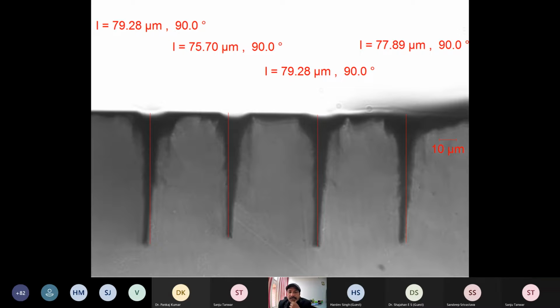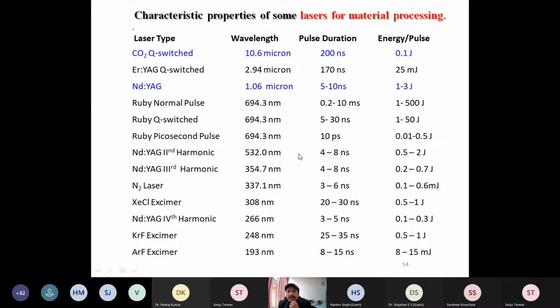So what type of structures or grooving can you do? This is the case of glasses that I did with the help of femtosecond laser. We use 800 nanometer with very small power, and you can see here around 75 micrometer depth can be achieved. Then we have a variety of lasers starting from CO2 laser to argon laser and other lasers.